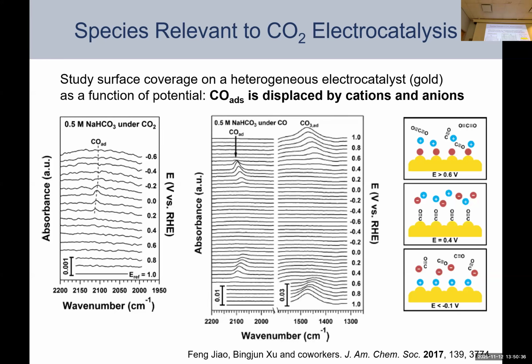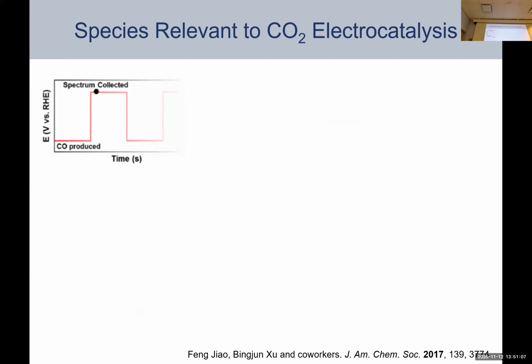So our explanation for this is that, well, from CO2, you obviously need to generate CO, so we need to be applying reducing potentials. But the negative potential loss of CO is essentially just exclusion and displacement by solvent and cations. Okay, so this is actually a bit of a complication because you can't just apply the potential where you want to generate CO and hope to see it on the electrode, right? Because it's gone. And so this required a little bit of a crafty trick. So they use a square wave pulse where they apply a negative potential to generate CO from CO2 and then collect the spectrum at a different applied potential and just toggle between these two.